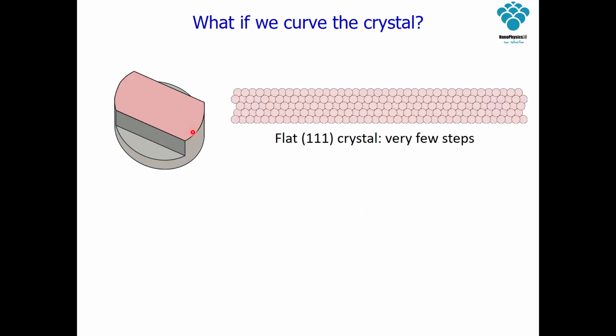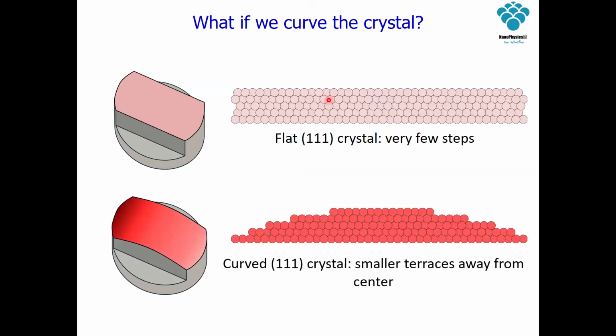So what we do, where we are experts in our labs, we take a single crystal that you have here. We have a very nice atomic order of our atoms. So everything in place. So for example, this is a 111 surface. And what we do, we curve that crystal. So we polish this single crystal in a certain way that you see over here, that in the middle it is still the same, but then when we go from this middle to one of these sides, we introduce steps. So we cannot cut an atom by half, so we have a step and so on.